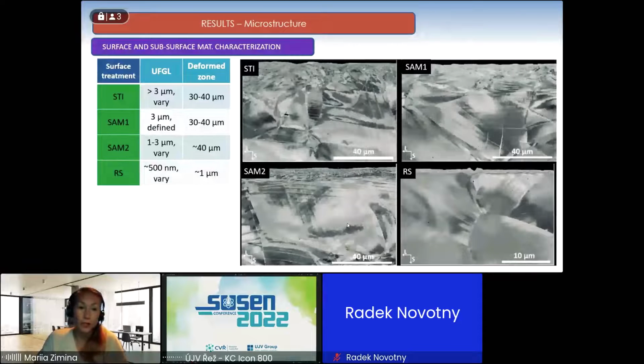So the results showed that first we obviously characterized all the surface and subsurface characteristics of all four surface conditions, and we can see here clearly that in all cases we have ultrafine grain layer under the surface, and in all four cases we have either slightly deformed zone or heavily deformed zone underneath this UFG layer. And so obviously the thickness of this layer varies with different applied stress or deformation. And so we calculated the thicknesses of these layers, and you can see that for STI, for example, it's more than 3 microns,